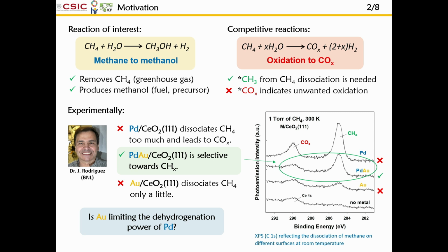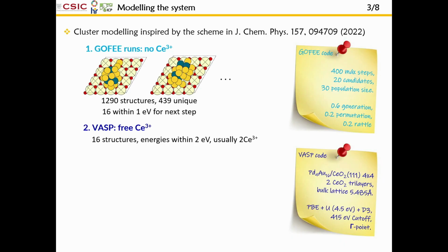So in order to study this, we wanted to study the reaction mechanism on a bimetallic nanoparticle. But to do that, you have to first come up with a model, and we used a scheme based on something that was already reported. So we used two computational techniques, the conventional DFT optimizations with VASP that you probably know, but also we used the GOFEE algorithm. It is an evolutionary algorithm, which means that it does not only generate a lot of random structures, but it also directs the search using first principles, because it starts from a population and does DFT single point calculations, and then builds a machine learning model that maps the energy landscape, so that when you build subsequent random structures, you can use this energy landscape to relax without using DFT calculations, so this is very fast.